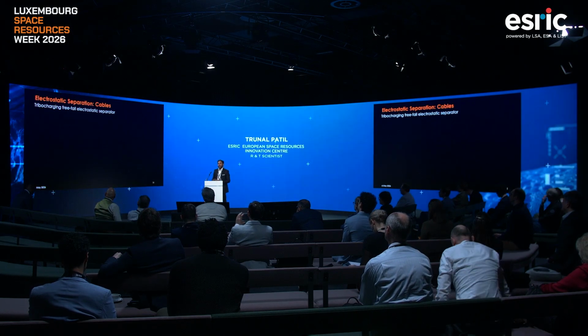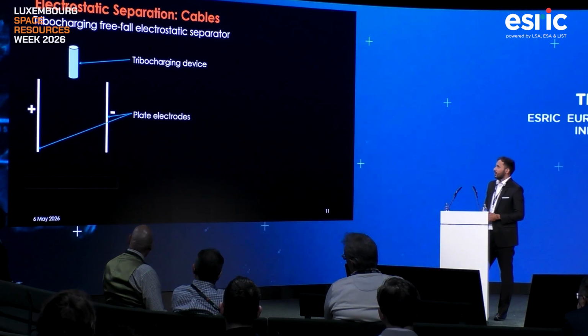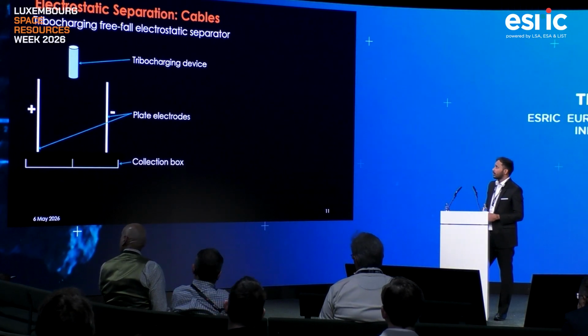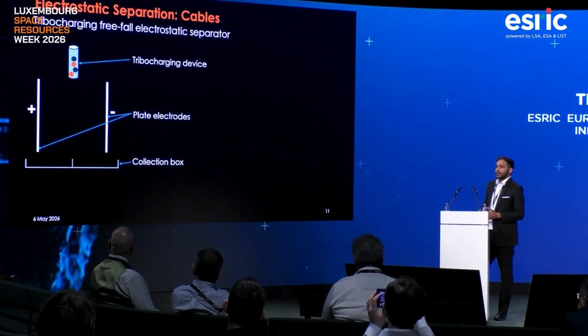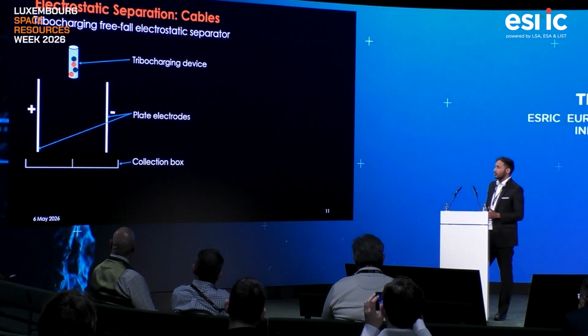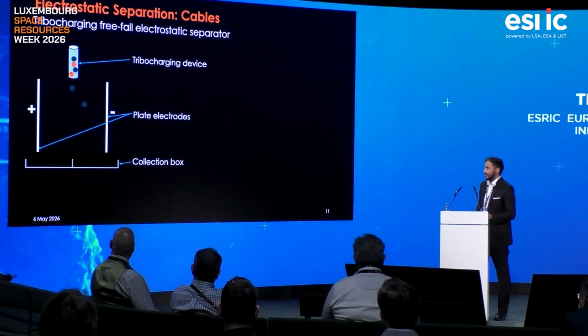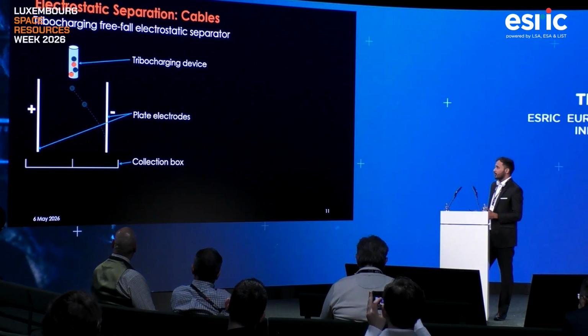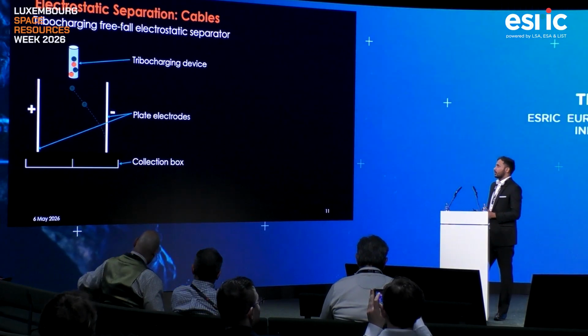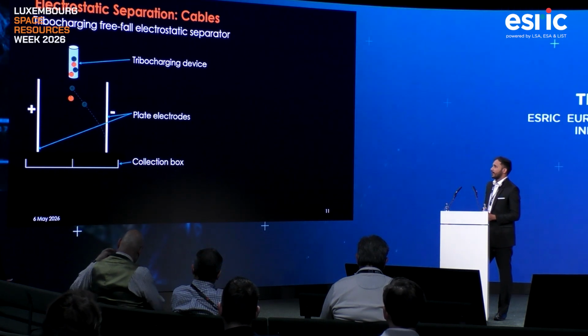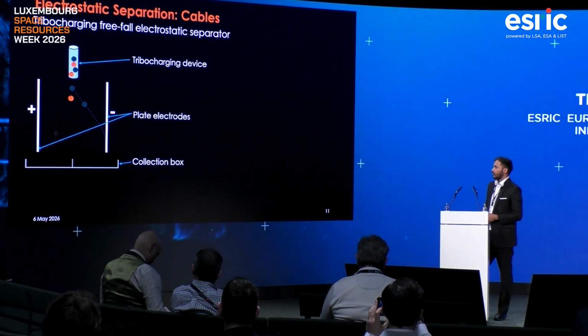In the next step, once we do the size reduction process, we also wanted to separate these materials. What we use is a triboelectric free-fall electrostatic separator, in collaboration with Imperial College London. The material is fed from the top into the triboelectric charging device, and based on its properties, each particle gets a positive or negative charge. When the charged particles free fall between two plate electrodes, positively charged particles are attracted to the negative plate electrode, and negatively charged particles are attracted to the positive plate electrode. That's how the separation happens. We use this electrostatic separation to separate metal from non-metal particles.